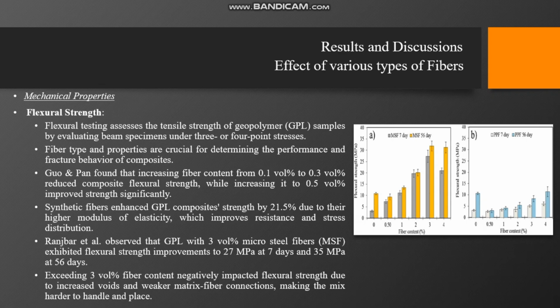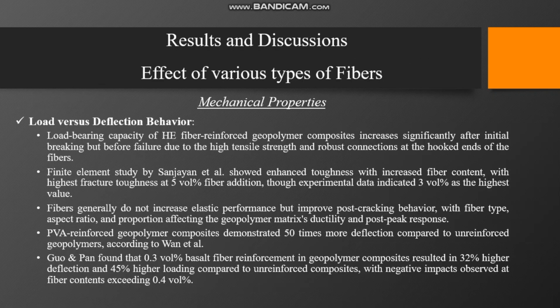However, the strength increased when fiber content was raised to 0.5% of the volume, with 0.5 volume percentage producing the best results. Synthetic fibers notably strengthened the geopolymer composites, showing a 21.5% increase over reference specimens due to their high modulus of elasticity, enhancing the resistance and stress distribution, as you can see in the figures. Next, we have the load versus deflection behavior.